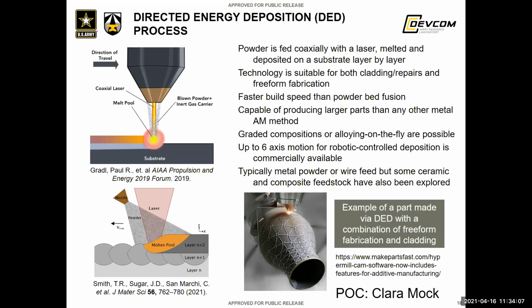So we're able to use this to create 3D parts, obviously not with the same resolution as we could with powder bed fusion, but it allows us to create, say, larger parts because we're not as restricted by build space as we are with the powder bed fusion machines. And then, as I said before, it's capable of building large parts, it's faster, and there are a lot more laser processing parameters, and a lot more parameters in general that go into the DED process.